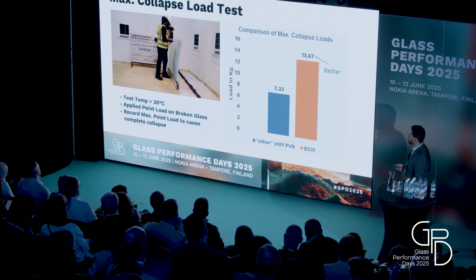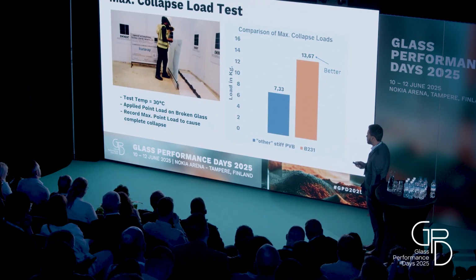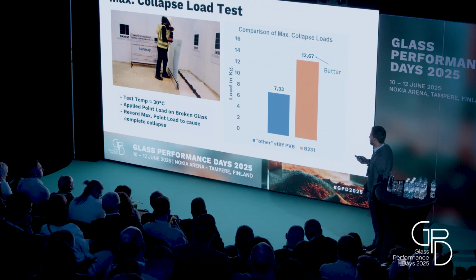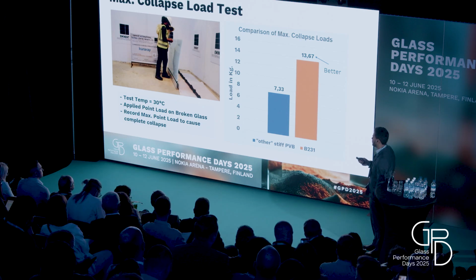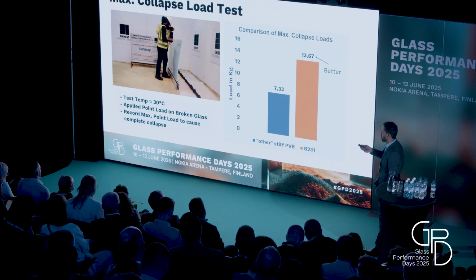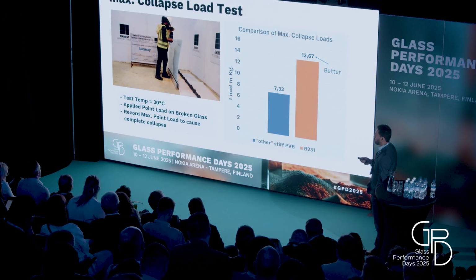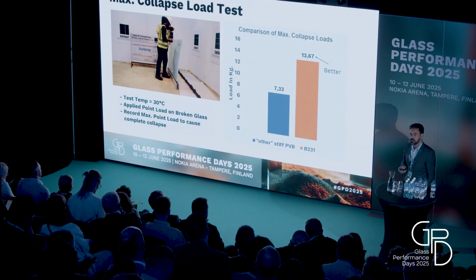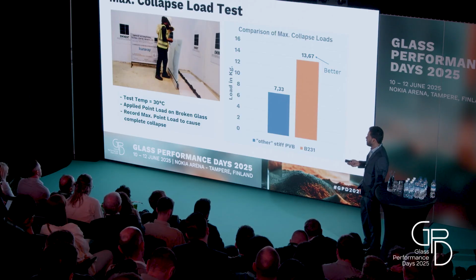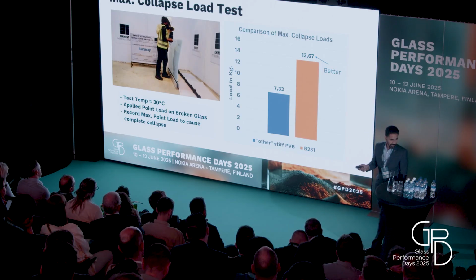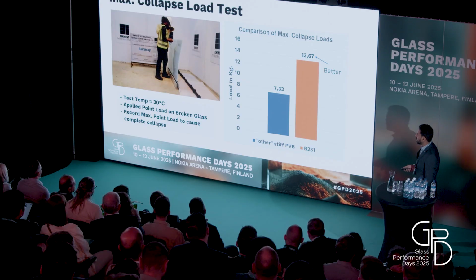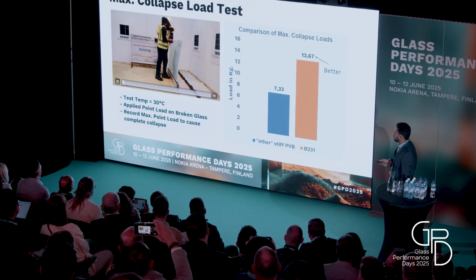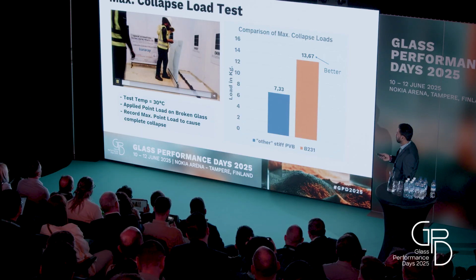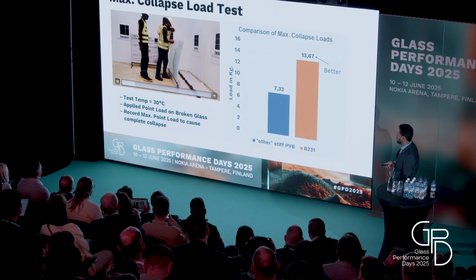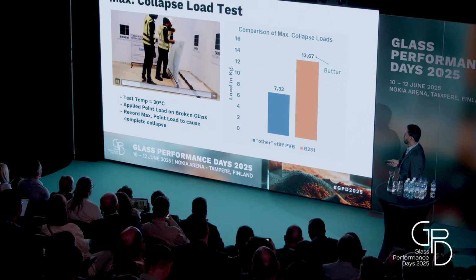Then we did another test, which is not as per any of the standards. What we did is we wanted to see, if there is a glass balustrade where both the glass layers have been broken, what is the amount of load that is required to cause the complete collapse of the panel. So I have a video to play here. We intentionally broke the glass, and after the breakage, we applied a load onto the top edge of the glass, to see what's the maximum load it can sustain before its complete collapse.